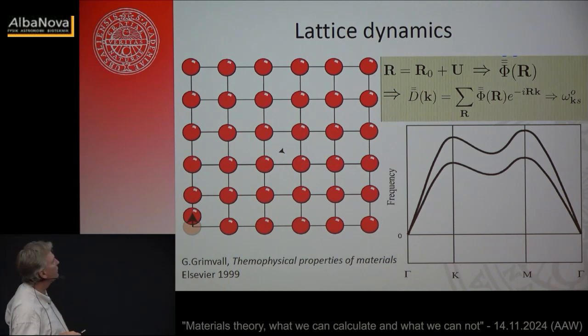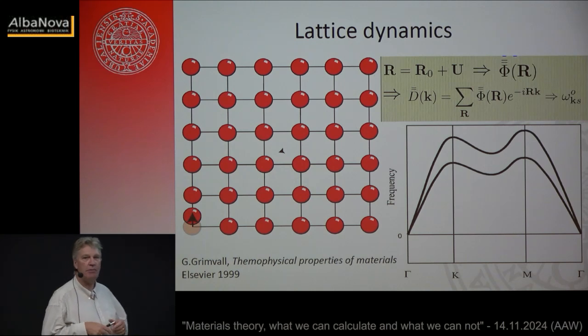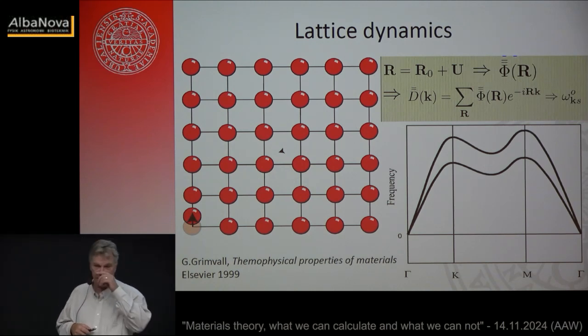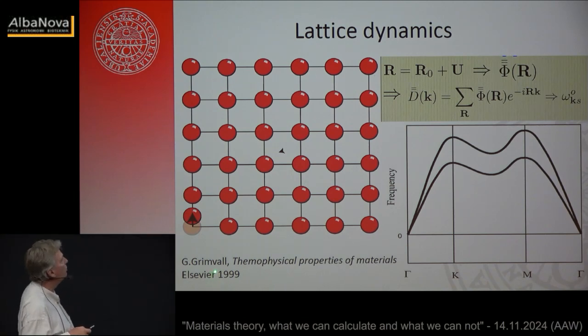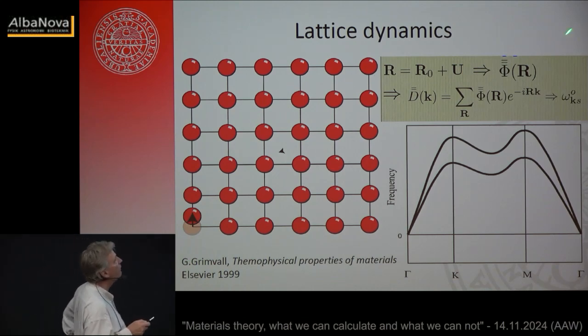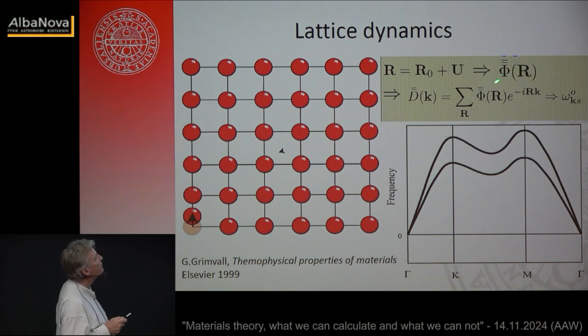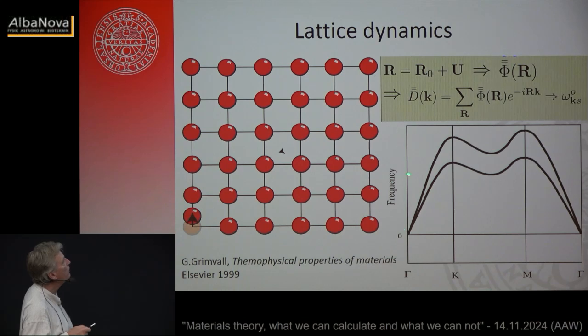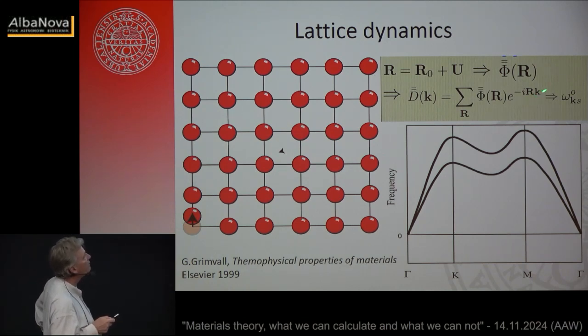Here comes maybe my favorite slide, because I can point to this very nice book by Göran Grimvall on the thermophysical properties of materials. Lattice dynamics. So if you can calculate lattice stabilities, maybe you want to also understand a little bit about phonons and lattice dynamics. So it's a well-known way to do that, and if you have forgotten how to do it, I encourage you to go and look here. What you want to have is access to a pair interaction potential, and then you do a Fourier transform of that to get a dynamical matrix, and then you diagonalize that, and voila, you have the phonon frequencies. And typically you get the frequency as a function of, again, a crystal momentum or information from reciprocal space, and that's the same K as you do in this Fourier transform here.